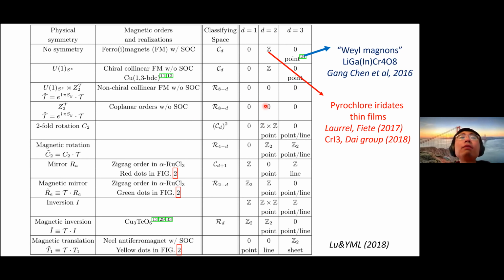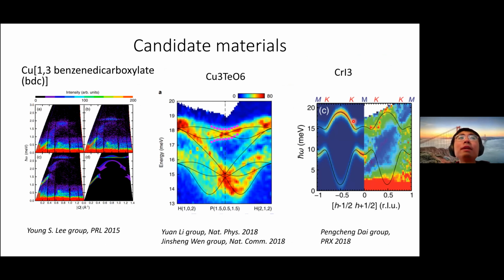It's helpful to look into materials which have been discovered so far: this copper BDC metal-organic framework, copper telluride oxide, and also chromium triiodide. In this example, except for the middle one, the other two both seem to have fairly strong spin-orbit coupling. For example, the Dzyaloshinskii-Moriya interaction is responsible for the opening of the gap at K. In chromium triiodide, the spin-orbit coupling is also very strong.